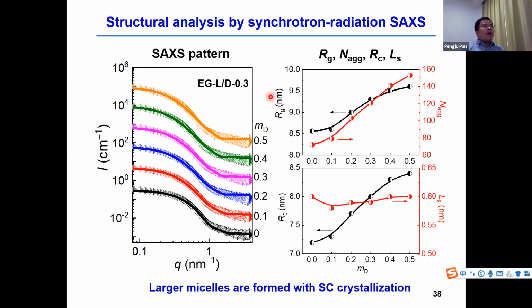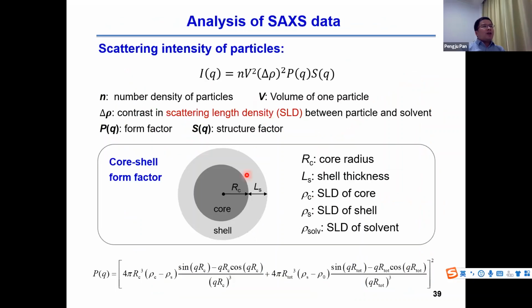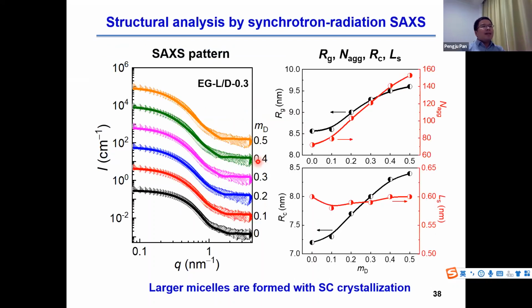We think the different thermal response sensitivity is related to the micelle structure. We analyze the micelle structure by solution SAXS. We use the core-shell model to fit the SAXS profile and obtain the micelle structure such as the gyration radius, the aggregation number, the core radius, and the shell thickness. The aggregation number means how many copolymer chains associated in one micelle.